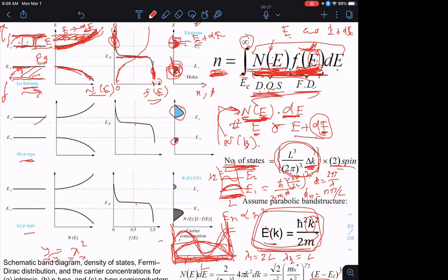So the nice thing is, you find that the spacing of these allowed energy states in terms of the variable k, the wave vector, is uniform, because n goes as 1, 2, 3, etc., times pi over L. That's why it's convenient to first count allowed states as a function of k, because these are going to be equispaced in k space, okay?